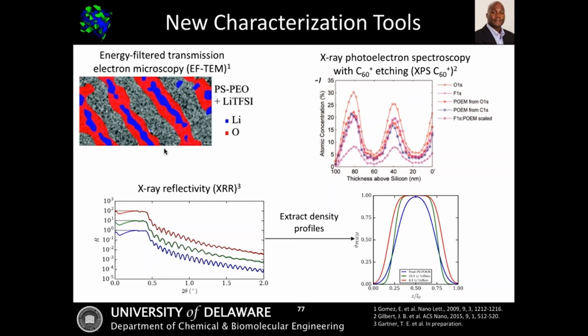And one of the things that's become a bit in vogue recently is actually using things like X-ray reflectivity or neutron reflectivity, again, to extract density profiles. And as you can see in the bottom right, that density profile looks very similar to the theoretical simulation work from de Pablo on the previous slide.